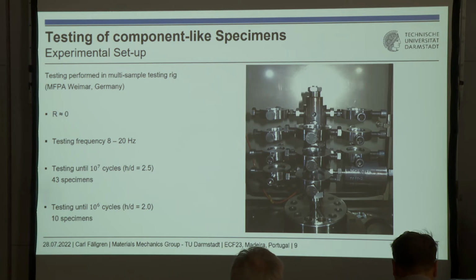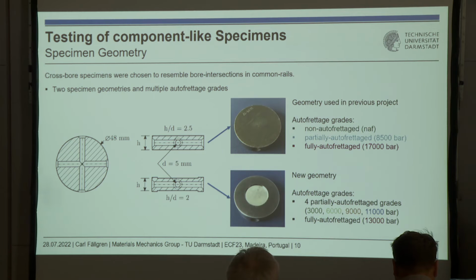Testing frequency was 8 to 20 hertz, so they varied that a little, and testing was until 10 to the power of 7 cycles for the h/d specimens with a ratio of 2.5. And it was tested in another way with those thinner specimens. There we tested in a load raising technique. That means we tested all specimens, and if they survived 10 to the power of 6 cycles, then we increased the load and we tested again, and so on, and so we produced a lot of runouts. But it was only 10 specimens tested.